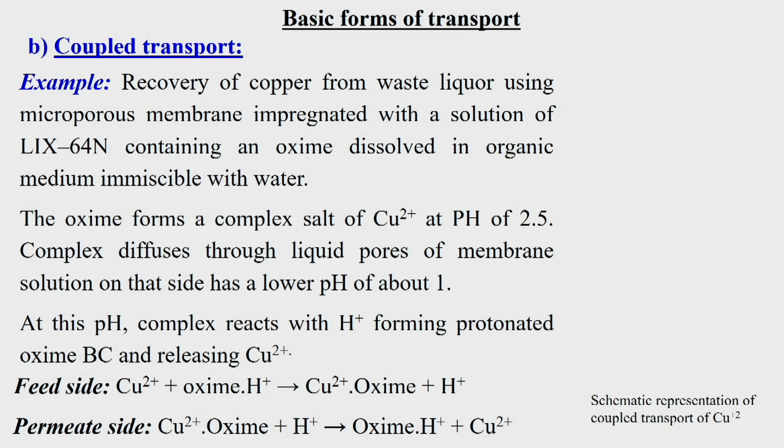The oxime forms a complex salt of copper 2 plus at pH 2.5, and the complex diffuses through the liquid pores of the membrane. The solution on that side has a lower pH of around 1. At this pH the complex reacts with H plus, forming protonated oxime BC and releasing Cu2 plus.